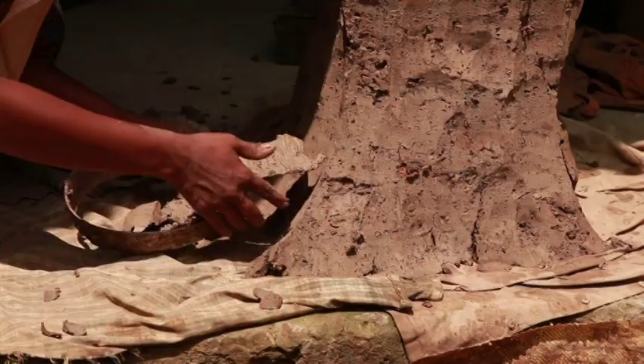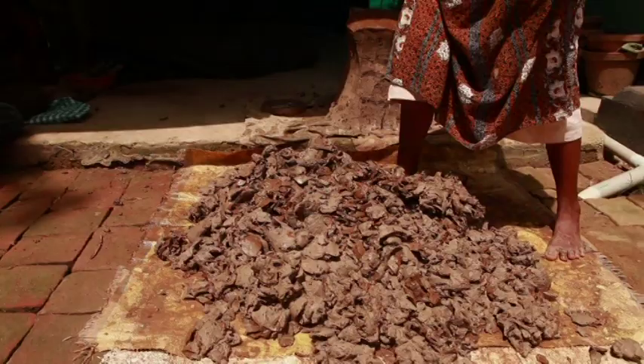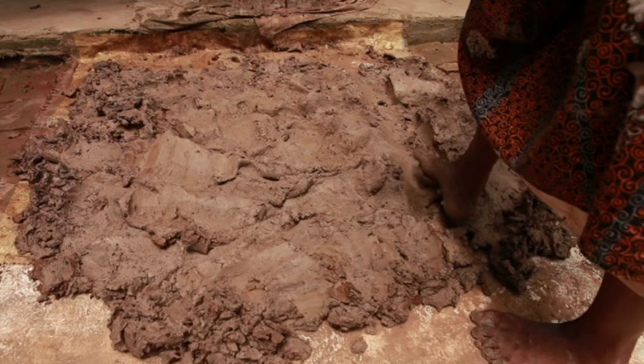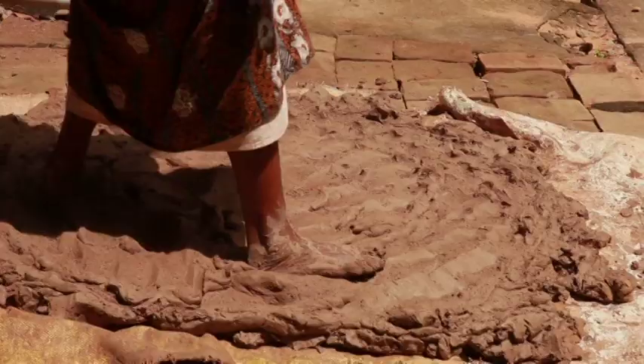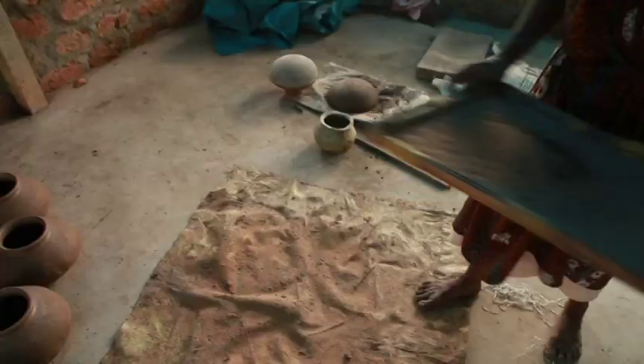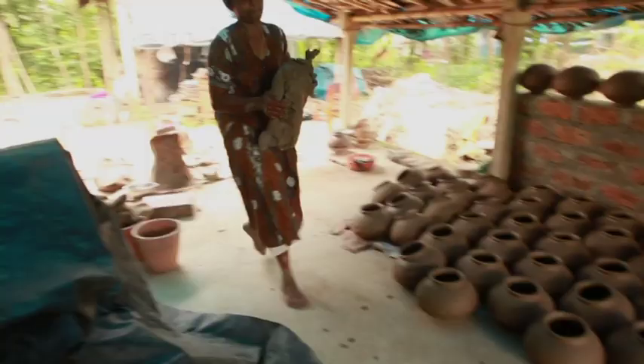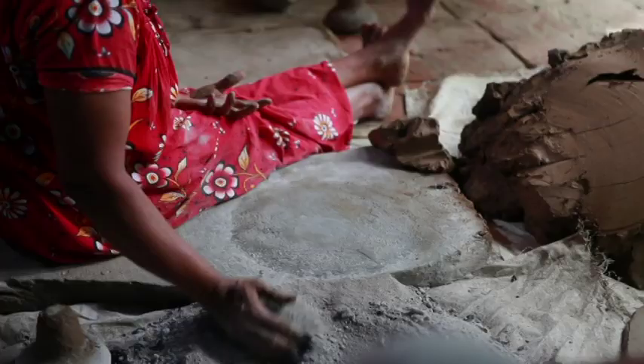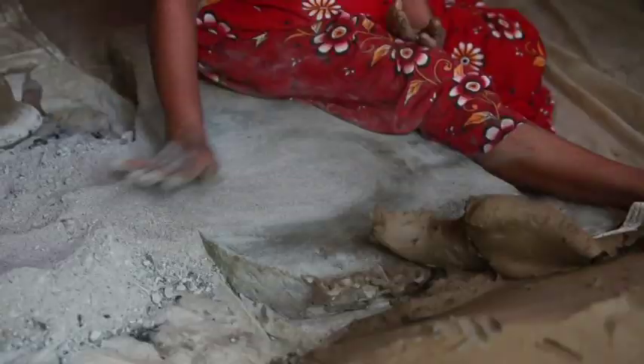The sequence of manufacturing the mattam starts with the preparation of clay. The potter takes the clay for a batch of pots and begins to trample it, periodically adding water. This helps remove air pockets and brings the clay to the appropriate consistency. Sieved fine sand temper is worked into the clay, preventing it from adhering to the floor and allowing the potter to change the properties of the clay to suit the function. The trampled clay is then taken to the area where the second stage commences.